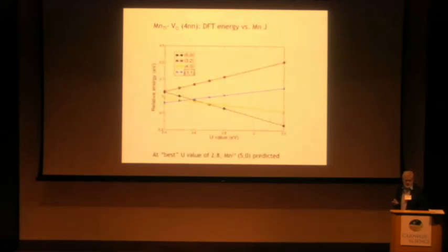But we had looked at this GGA plus U, and saw what would happen if you varied the value of U. And in this case, it actually changes the predicted ground state. So this is quite interesting, because do you really trust for predictive abilities that if you found that you could fit U equals 2.8 for manganese based on the bixbyite manganese 2O3, that it should also apply to a manganese substitution in strontium titanate?